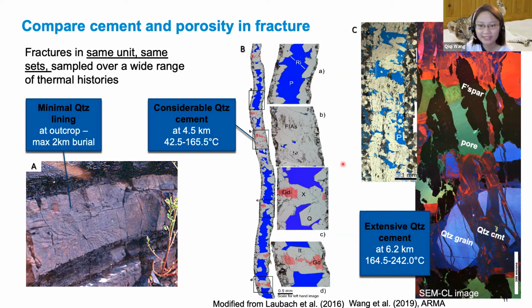And I want to emphasize that even in the most deeply buried, hottest examples, we still got cement bridges texture, and we still see a lot of open pore space. Now, I would like you to pay attention to some features in this rightmost image. This is a representative internal texture of a natural fracture with quartz cement, actually from the same core, from exactly this core right here. And this image is from a 6.2 kilometer depth, so pretty deep.